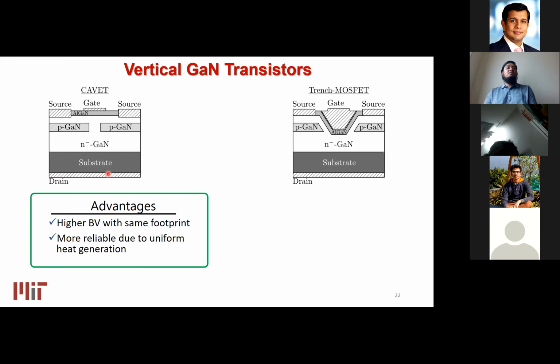Just to explain how this device works, as we see, we have a drain at the bottom, and then we have this N-minus GaN, which is the drift region. On the top, we have source and gate, and here is the channel region. The main challenge of these devices is these P-type regions. That's called the current blocking layer. This layer has to be introduced so that the device can turn off. It's similar to the silicon power MOSFETs I showed a few slides ago.